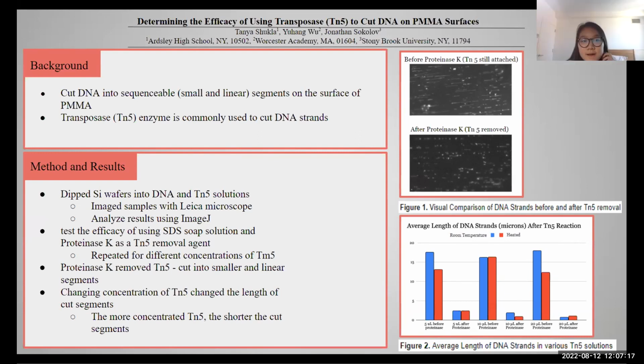So once the TN5 is attached to the DNA strands, it cuts the strands, but the strands will not be separated until the TN5 is taken off the strands. Therefore, we tested the efficiency of using SDS soap solution and proteinase K as a TN5 removal agent and compared the results. We later determined that proteinase K was a better removal agent.